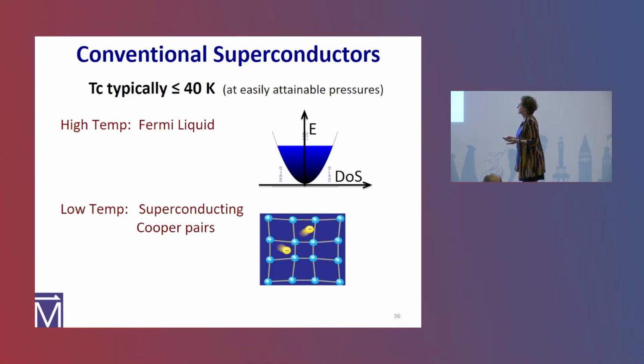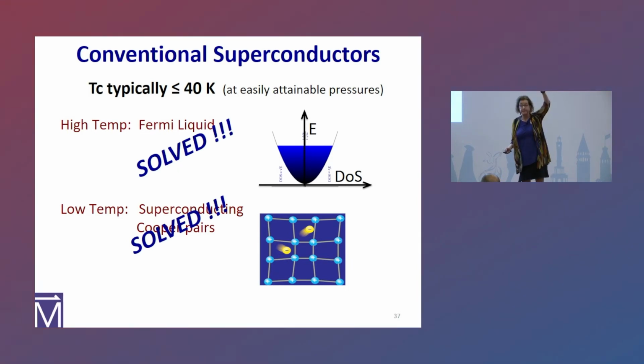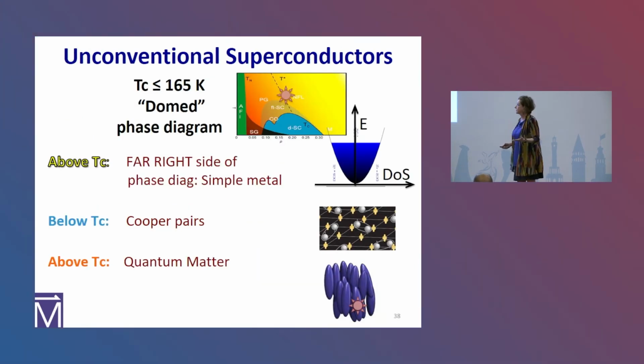So moving along here, conventional superconductors are typically less than 40 K, like niobium, niobium-3 tin, and at high temperature, it's solved. It's a Fermi liquid. At low temperature, they're superconducting pairs. So you go from high temperature, where you have a simple Fermi liquid, into a phase transition, it's a real phase transition, right? You're creating and destroying quasi-particles and Cooper pairs. It's really cool. But it's solved. We got this one. What we don't have is this one.